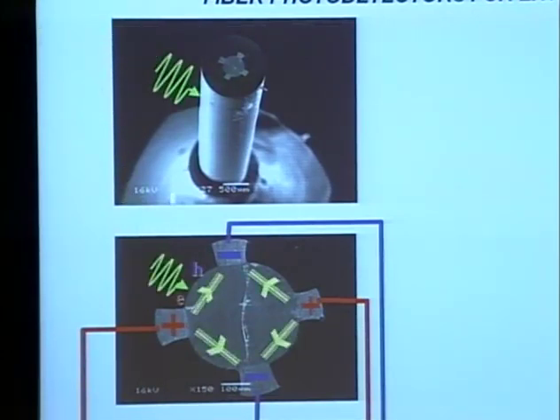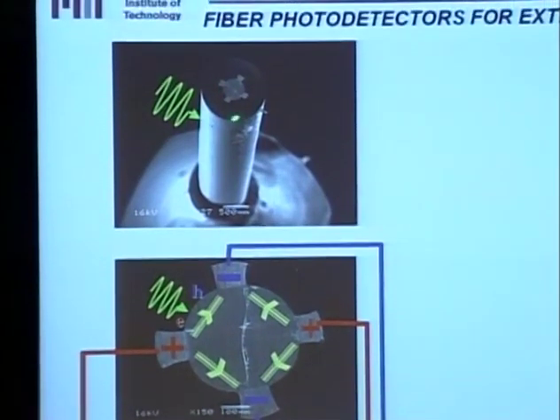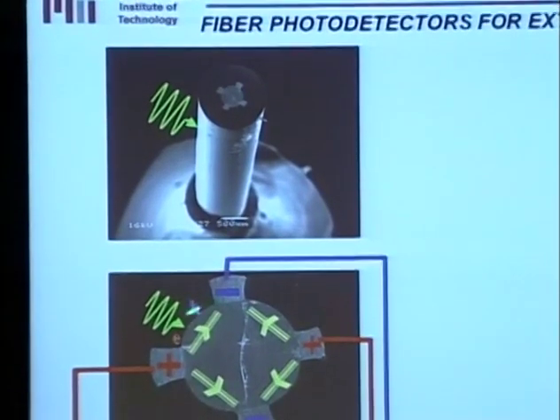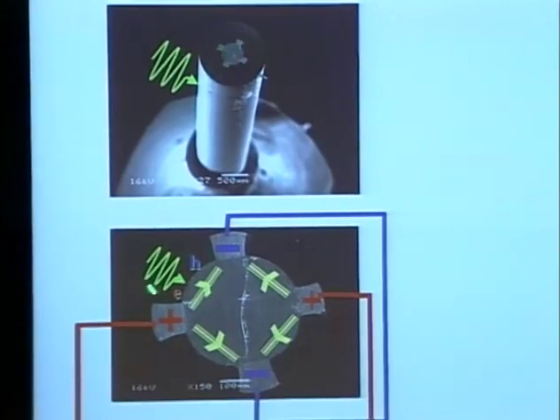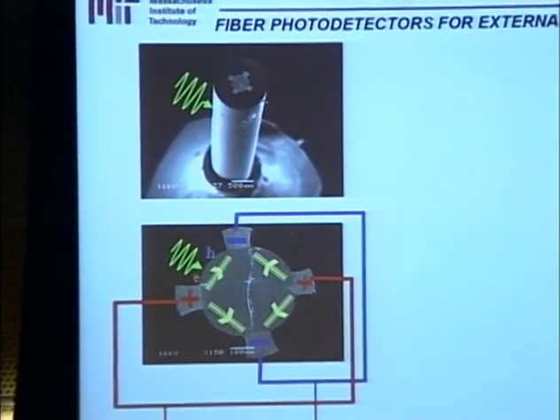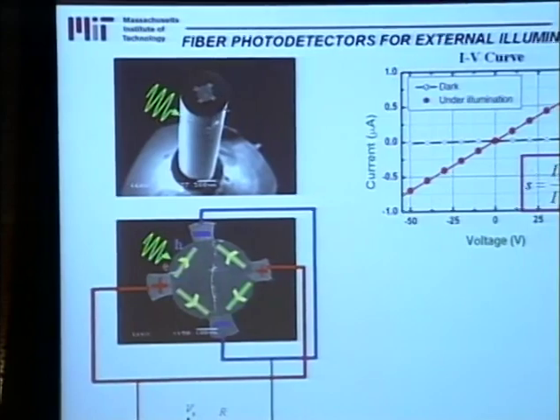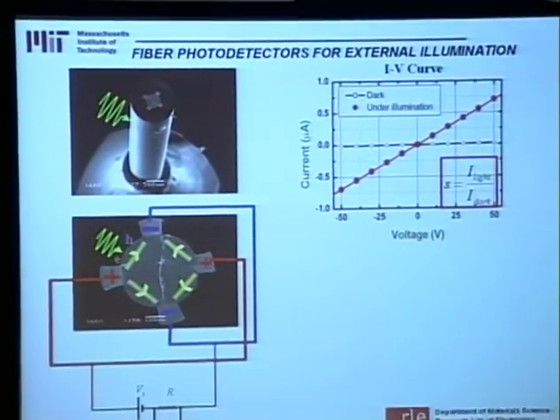So here is the fiber. This is a cross-sectional SEM. You illuminate it with light. You bias the electrodes. These are where the electrodes are. You excite electron-hole pairs. That changes the conductivity of the fiber. And basically, you have a photoconducting photodetector.